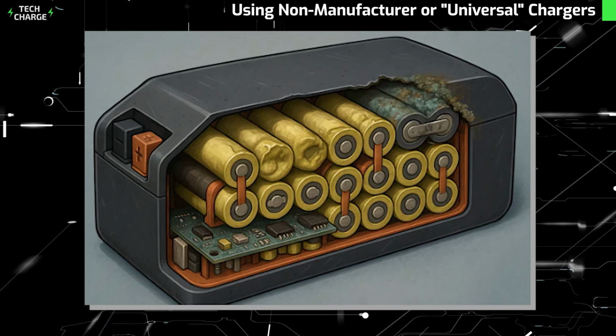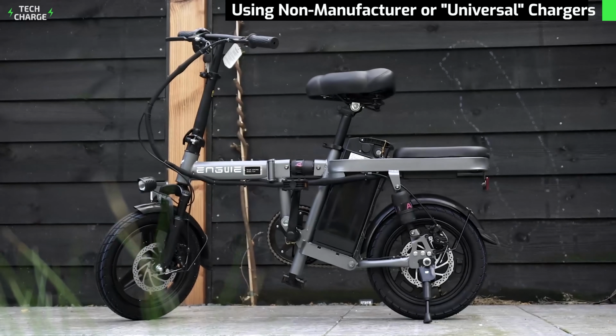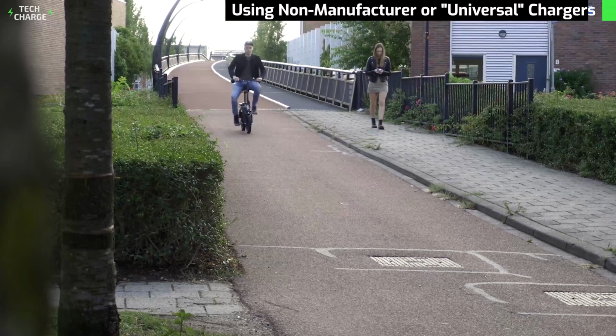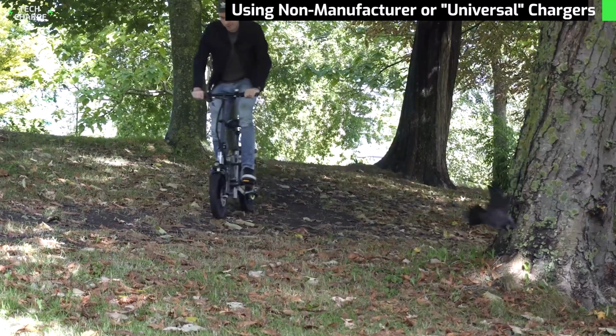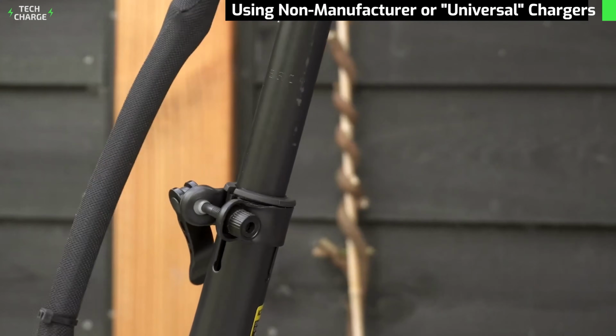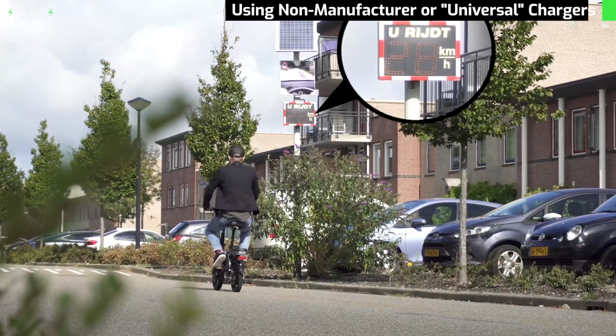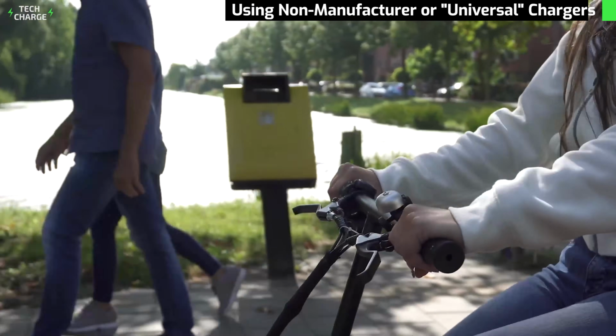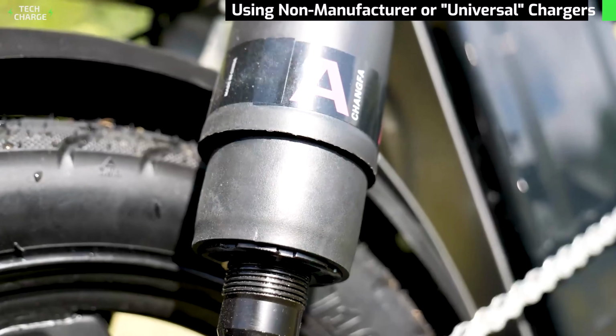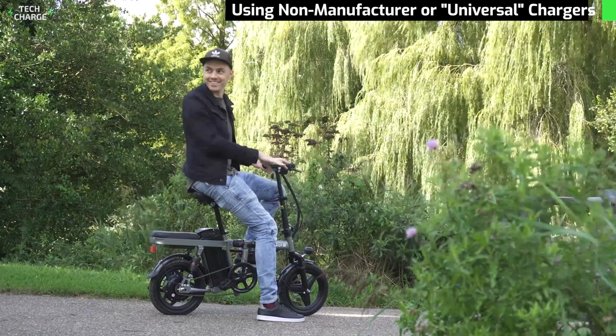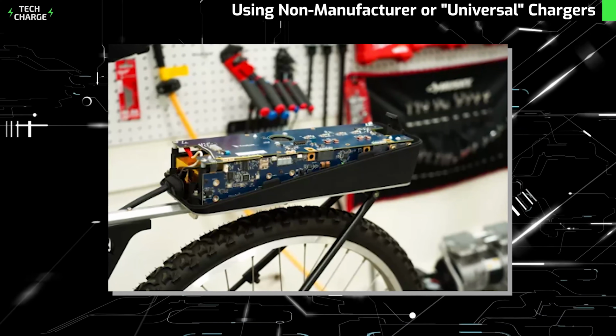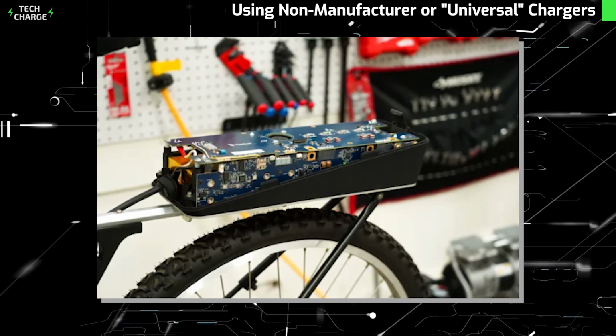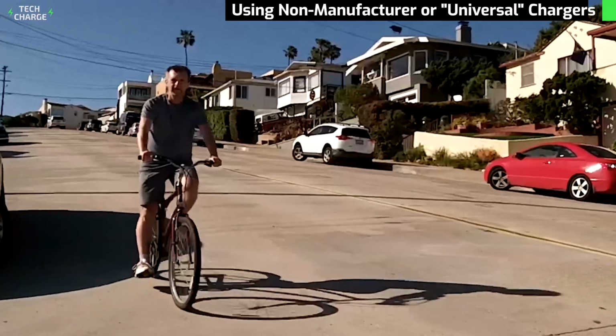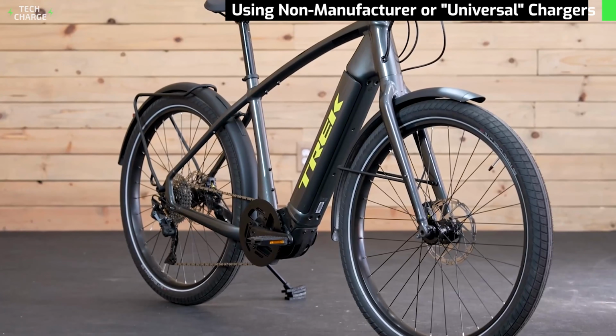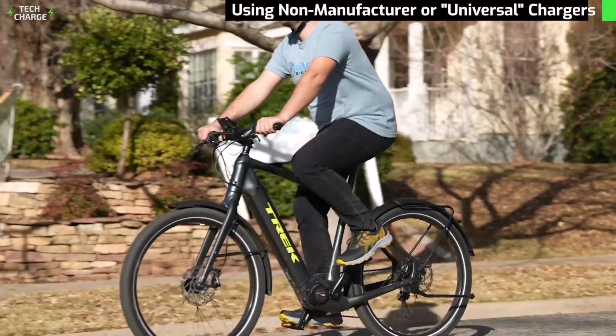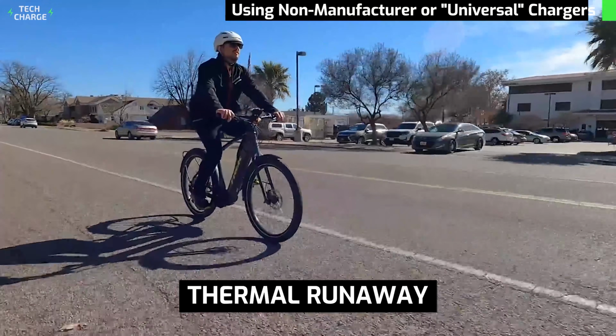Wrong current creates localized hotspots during charging, as some cells heat faster than others due to uneven charging rates. These thermal gradients put mechanical stress on the internal components. The result of sustained electrical stress from an incompatible charger is excessive internal heat buildup that overwhelms the battery's thermal management capacity. This heat accelerates electrolyte decomposition, creating a feedback loop. As the electrolyte breaks down, internal resistance increases, which generates more heat, which causes more decomposition. This runaway thermal process is exactly what the term thermal runaway describes.